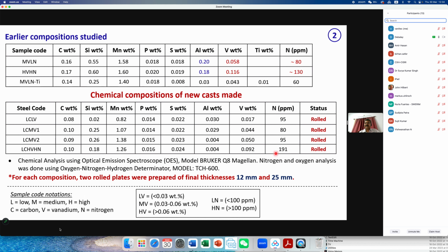Nitrogen, this time we are using, for these grades, nitrovan received from Vanitec. So these are the nitrogen levels achieved with the nitrovan received from Vanitec. Thanks to Vanitec for the same. For each composition, two rolled plates, 12 mm and 25 mm, we have coded them like low vanadium, LV, where vanadium is less than 0.03, medium vanadium 0.03 to 0.06, high vanadium greater than 0.06. Likewise, low nitrogen less than 100 ppm, high nitrogen like that.